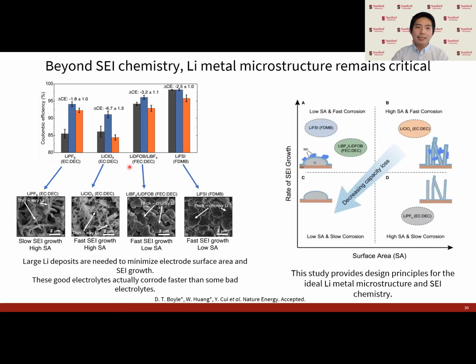And from measuring these existing electrolytes, we can start to classify them or group them into different categories among these two metrics. So we can identify fast corroding high surface area systems, such as the perchlorate in EC/DEC, and these are going to have the worst storage stability out of anything shown here. We can also identify high surface area chemistries, but with slow corrosion kinetics. For example, this PF6 in EC/DEC, which is fairly good among all the candidates in storage, but shows very bad cycling performance, which makes it not viable.